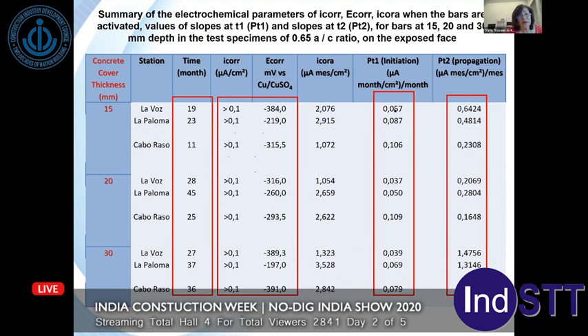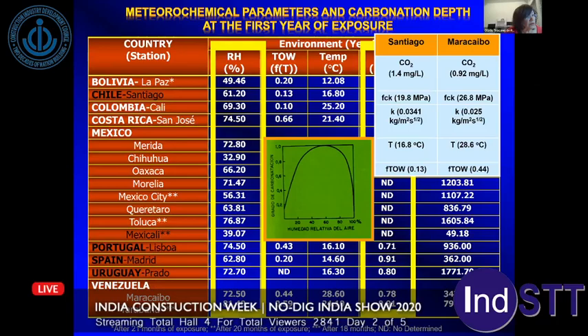When we consider these environmental parameters together with the characteristics of the concrete, cement content, and effective porosity, we found that the Santiago test site in Chile has the most potentially aggressive combination of environment: 1.4 milligram per liter of CO2 with 61.2% of relative humidity, and concrete properties, 0.0341 kilogram per square meter per second to a half of water absorption, suggesting it is the fastest carbonation area in the test sites analyzed so far, as it is shown in this table.